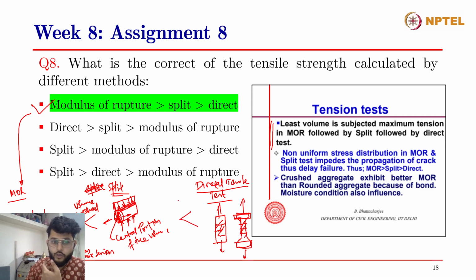Therefore, the involved volume is again higher in the case of direct tensile strength test, right? So this is exactly why the more the volume that is involved in the strength test, the lower will be the strength. I mean that will be much nearer to the direct tensile strength, right? So in the case of direct tensile strength, the whole volume is subjected to tensile stress, and therefore it has the least tensile strength. Comparing this to the split tensile strength, only the central portion of the cylinder that is directly under the plates which is applying the load is subjected to the tension, and therefore it has a slightly higher strength than that of the direct tensile strength.